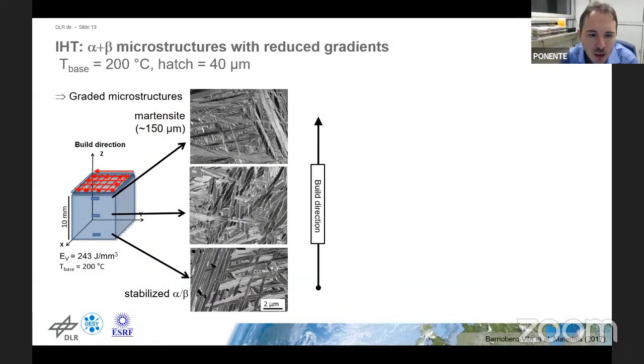And in fact, if you look at the microstructure along the height of a simple cubic specimen, you will find this kind of effect. Shown here is this very high energy parameter that I showed in the beginning, where we have this very strongly stabilized alpha-beta microstructure in the as-built case. And you see in the SEM images taken from the bottom and the center of the sample, this kind of very nicely stabilized alpha-beta microstructure with a lot of beta phase. Whereas if you take an SEM image from the top of the specimen, it's still this very martensitic microstructure.